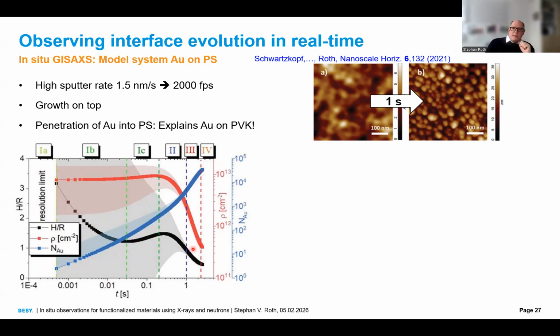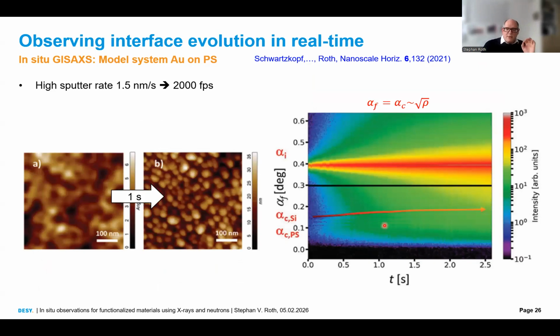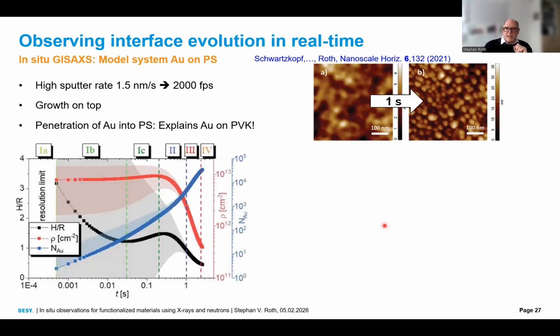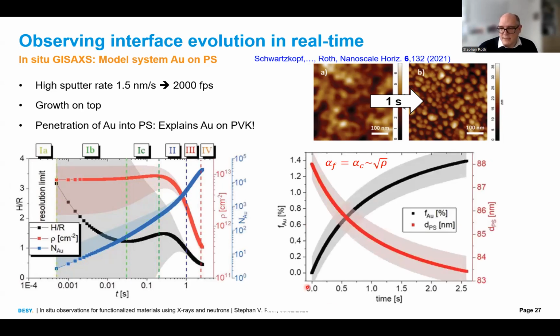But what is more important, we were able, via these fringes here, to analyze the polystyrene layer thickness and its density. And what we saw is these 2 lines here. See at the time, these are the first roughly 3 nanometers. This is not a solid line, but these are individual measurement points. But because we have more than 2000 frames per second, it looks like a solid line. What we used here is the remaining undisturbed polystyrene layer thickness, and you see it's decreasing with time. So we see that we have a diffusion layer where gold diffuses in with time from 0 nanometer to roughly 5 nanometer. And at the same time, we can tell you the loading of this diffusion layer. It's only between 0 and 1.4% of gold atoms which diffuse into a 5 nanometer layer.